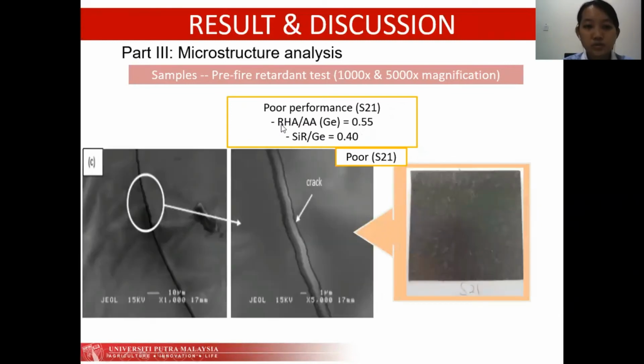So this is a sample with poor performance in the fire test. Before the fire test, we can see the silicone rubber is poorly incorporated into the geopolymer composite matrix. Due to the dominant geopolymer composite matrix, cracks and corrugated wrinkles developed during the curing and pressing process. The formation of cracks consequently provides openings, which allow the heat to transfer further into the layer of coating and lower the fire retardant properties.